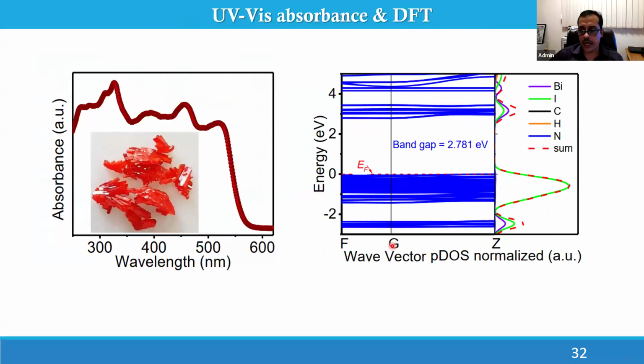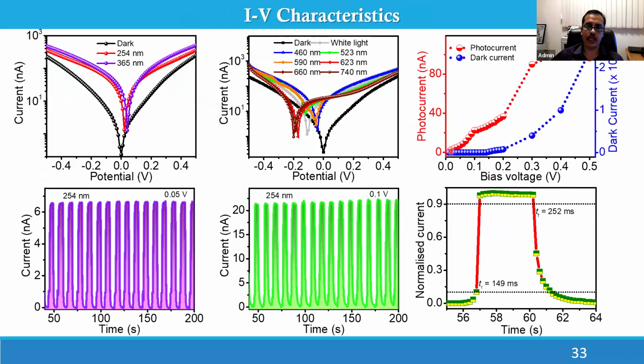And here we made a bismuth-based material. It is having a beautiful absorption up to 550 nanometer, and this is the band gap analysis we carried out for this material, and this is the photo detector analysis we did, and it is much faster. It is like the rise time is almost half compared to the previous report, and fall time also lower, and it is giving best efficiency for the 365 nanometer. 254 is also equally good, but in the visible region, the efficiency is low.